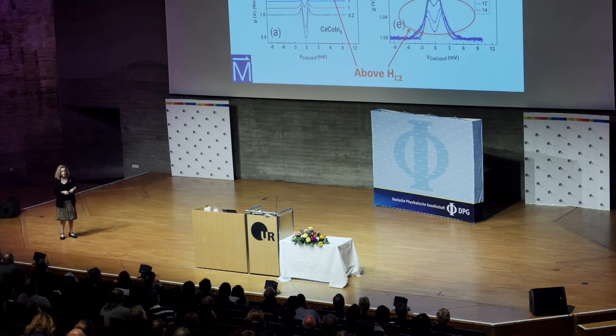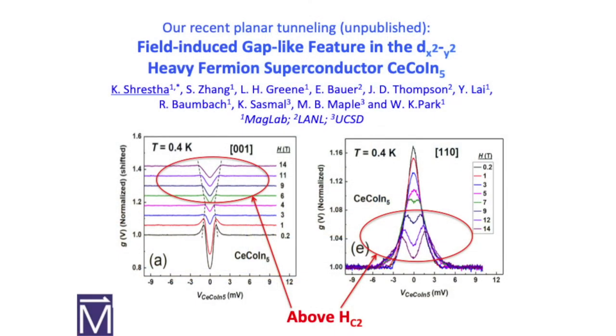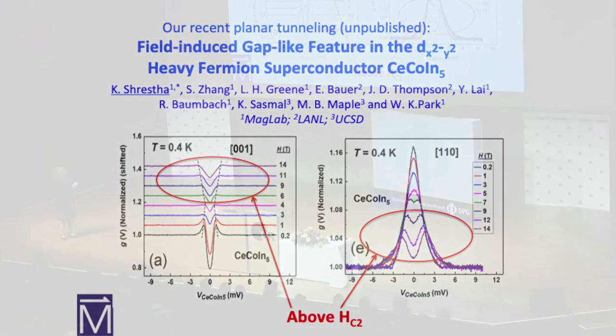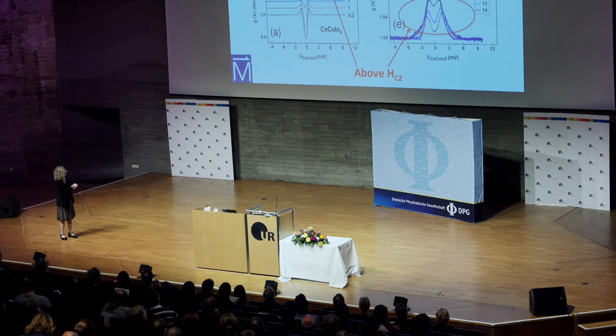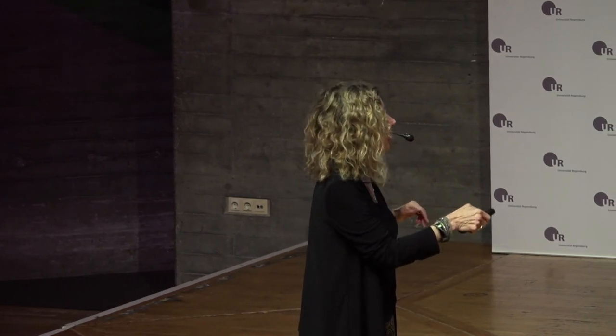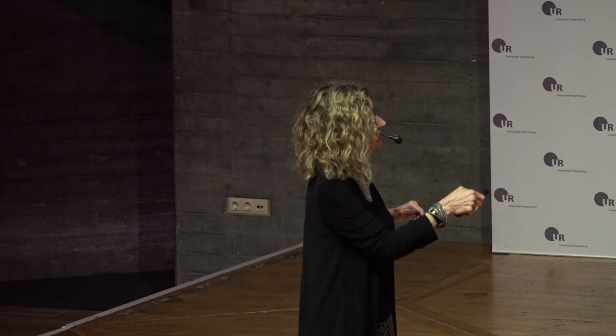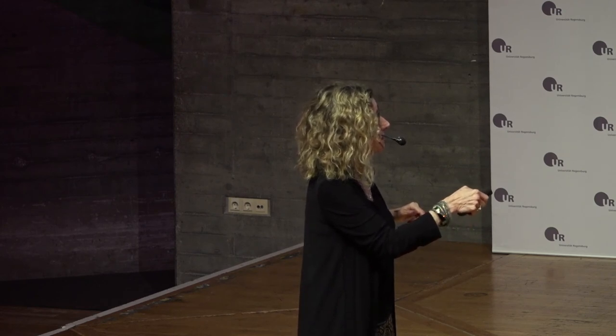So using our planar tunneling technique, this is normally what you expect for a d-wave superconducting gap in this heavy fermion. That's expected. But as you crank up the field, and we actually have done it up to 18 Tesla, we lose the superconductivity, and above where this material is not superconducting anymore, we're still analyzing this, we see a whole new gap come in. This is clearly not a Fermi liquid, and in fact, this is somewhat understood here. If you go in this other direction, in a dx squared minus y squared superconductor, you see the Andreev bound state, but as you go above Hc2, you see all this structure. So we have ideas, we're still analyzing the data, but here we have a whole new non-Fermi liquid.